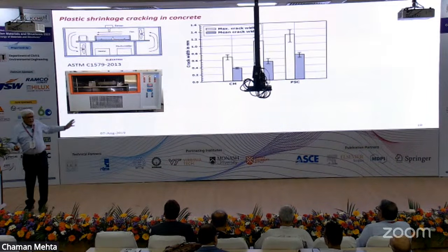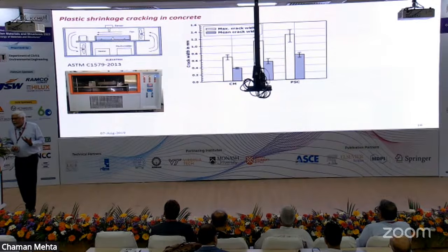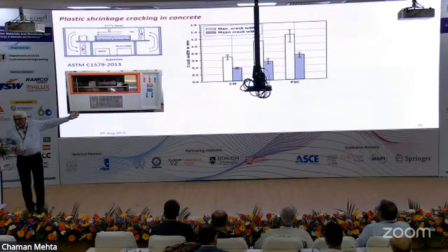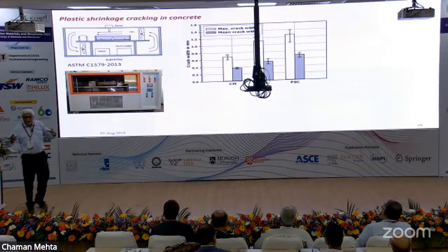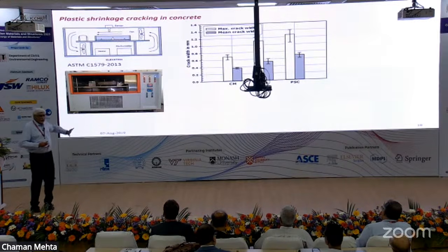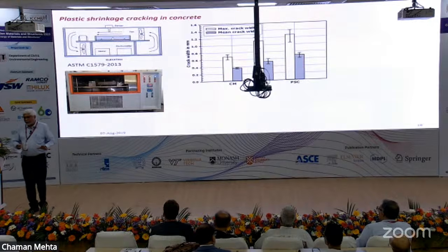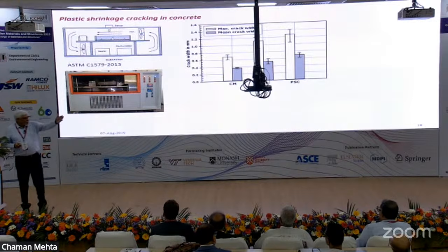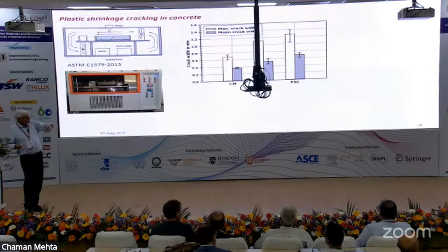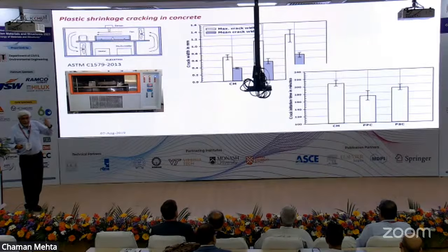So we started looking at what is going to happen when you have different types of cement. OPC is the ordinary Portland cement, PPC is with fly ash, PSC with slag. You see that the crack width is increasing. How did we do it? We take a slab of concrete, freshly made, put it into this chamber and blast it with hot air. I think Dinakar set this up when he was with us. Crack initiation time is becoming lesser.